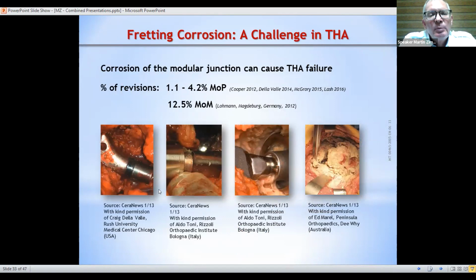Looking at some recent publications, specifically with cause of revision due to fretting and corrosion, trunnionosis, we can see that, based on different publications, you can have up to 4.2% of cases of revision if you are using metal on polyethylene articulation, and this can go higher than 12% with metal on metal. But as you know now, metal on metal is not used anymore. Still, with metal on polyethylene, up to 4% of cause of revision can come from the effect of trunnionosis.